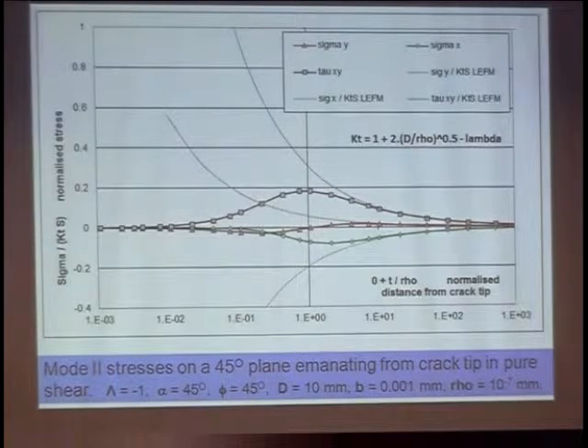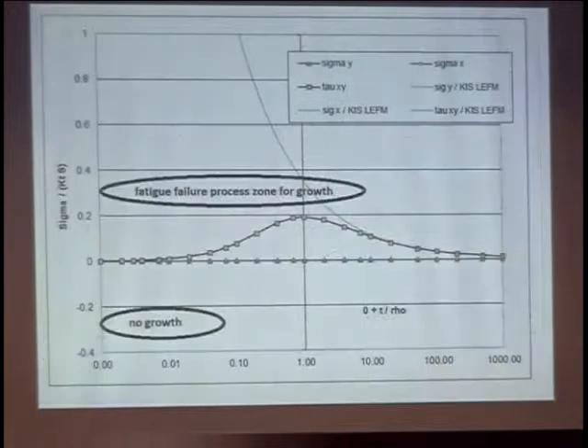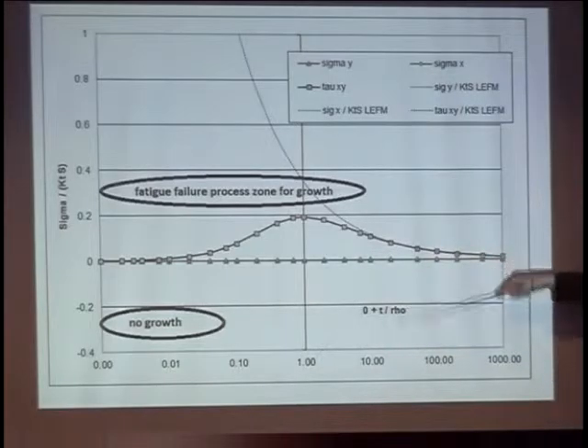And again, this is an invariant picture for mode 2. In fact, there are only two fundamental pictures, one for shear mode and one for tensile mode, which we had earlier. And those two pictures describe all the stress fields that you get for biaxial loading for any combination. Process zone. A few people have mentioned process zone already, and I never really quite understood process zone. I've always been a fan of plastic zones and things related to that. But when you think that this dimension here, defined by rho, the radius of curvature, that's tiny.